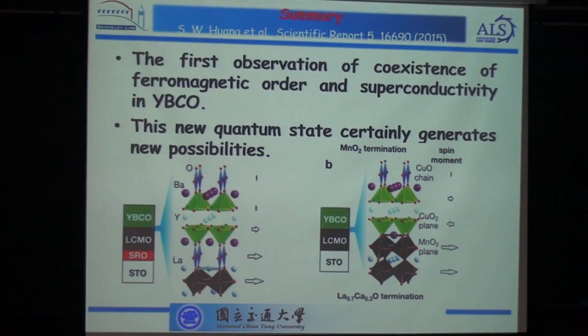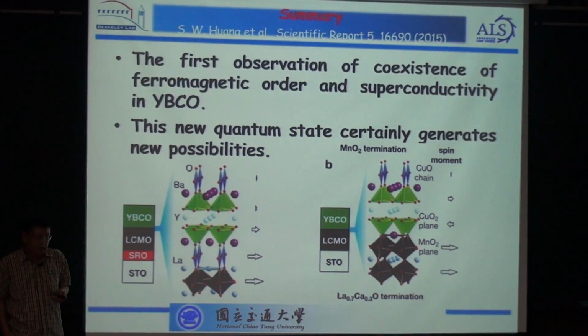So the conclusion is that we indeed observe the coexistence of superconductivity and ferromagnetism in this type of termination by this heterostructure. Then maybe there is a weak coexistence of the ferromagnetism and the superconductivity. So what? And this is new. Audience: So is it still d-wave? Pardon? Is this pairing still d-wave? I'm going to that in the next transparency.